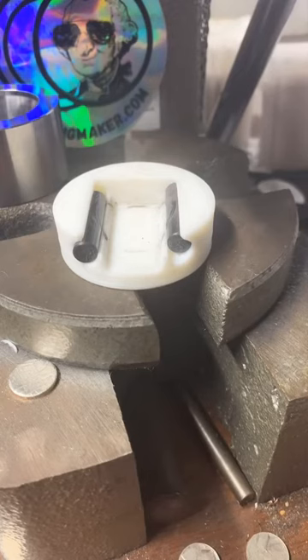If you clear my ring with clear spray paint, you think that would work? I think it would work for a little bit. Salt in your sweat and just rubbing back and forth has a way of working off whatever you put on these rings. That's why I suggest clear fingernail polish, just because it's easy to paint on, it's cheap, and you can do it as soon as you see the layers start to come off or your fingers starting to turn green. You just paint it real quick, let it dry, and you'll have a nice little clear protective layer on there. This does not want to focus.